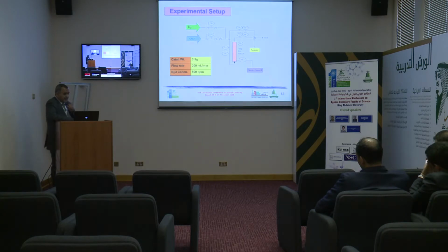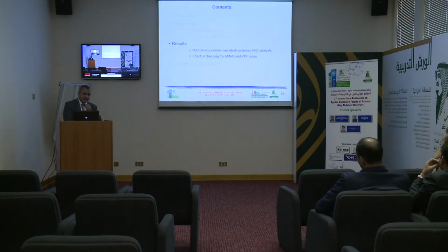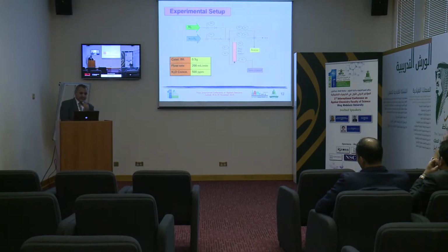Going to the experimental setup, it is a simple setup that contains two sources here, or two gases. The first one, nitrogen as a balance gas, and the other one is the N2O diluted in nitrogen. The required amount of nitrous oxide can be fed by using two mass flow controllers that go to the reactor, then to the analysis part. We used in most of our experiments a catalyst weight of 0.5 gram and flow rate of 200 milliliter per minute, and finally the N2O concentration was 500 ppm.